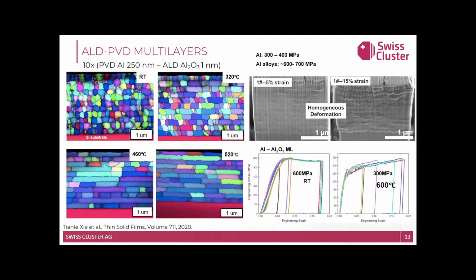Similarly, we anneal this type of coating, in which we go from room temperature all the way to close to the melting temperature of aluminum. So in this case, 520 degrees. And you can see from the EBSD images the grain size distribution, and as we go to 520 degrees, the ALD layers act as a thermal barrier layer, so it prevents the grain growth across the vertical direction and minimizing the grain growth along the